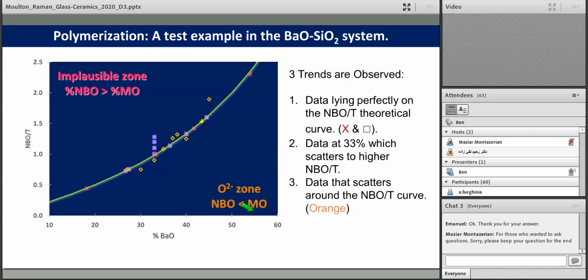So in terms of developing a structural model, I would say this introduces a very large error into the proposed structural models at hand. And to prove that's not just my opinion, I've collected all the data for the barium system. This is the same plot as before, but zoomed in a bit. Here's the ideal line, where K1 goes to infinity and all the free oxygen is reacted to form non-bridging oxygen. You see there are three trends in the data, and studies on this line almost always assume a priori situation one above, and so they force their models onto this line.